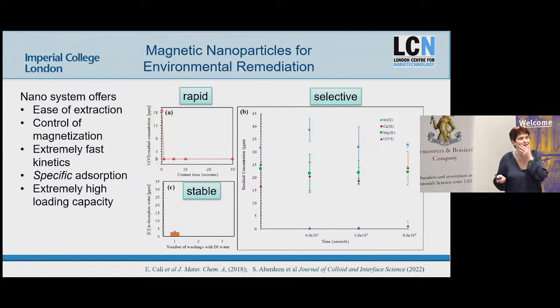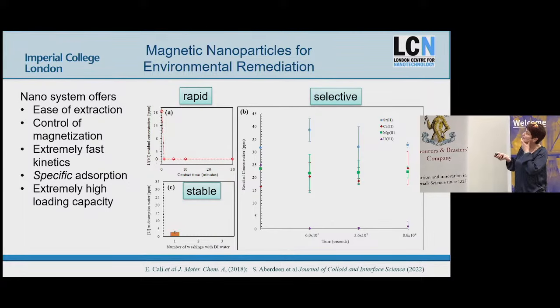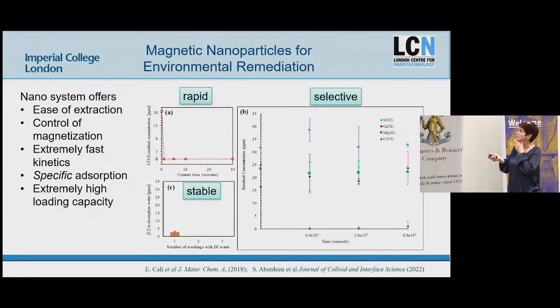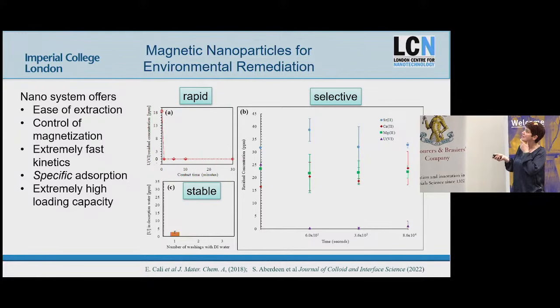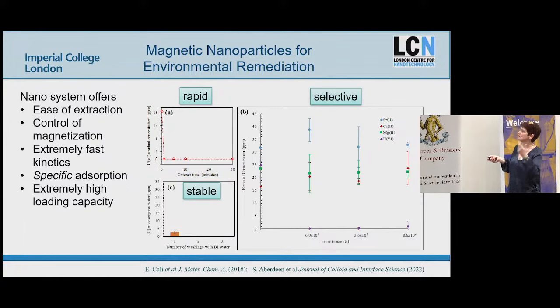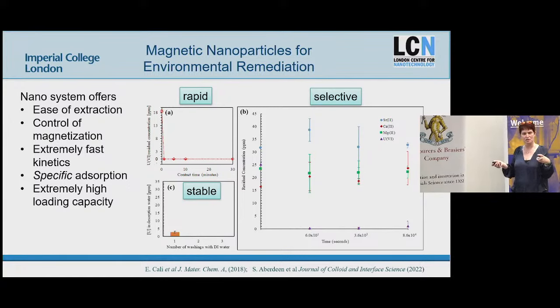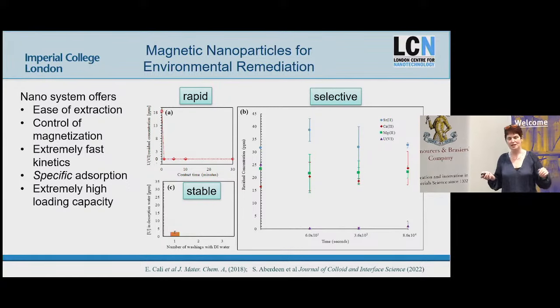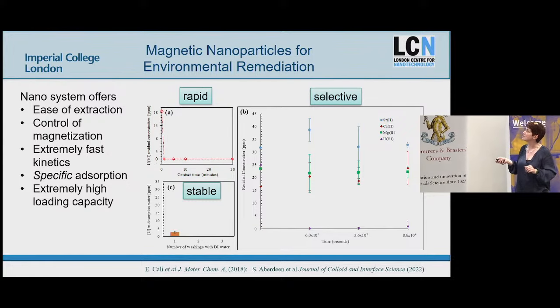And it works amazingly well, right? So it's super rapid. You take the uranium out in less than a minute from the whole solution, right? It's all removed. It's very stable. So this is if you wash the nanoparticle, because you might remove a little bit that's not touched, but then nothing else comes off. It's 95% stable in the system.